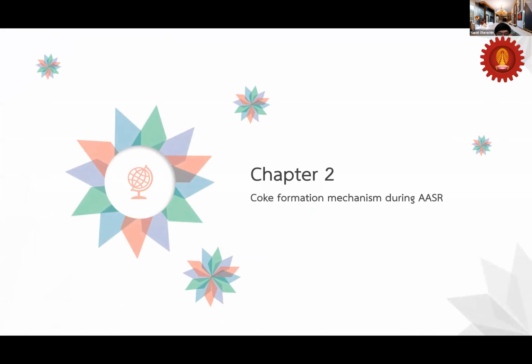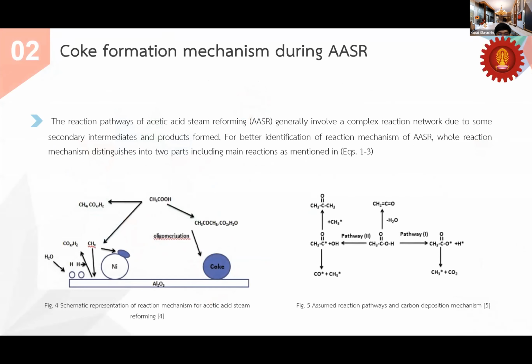Next is chapter 2. I talk about the coke formation mechanism during AASR. A simple reaction mechanism of AASR proposed in several studies is shown in figure 4 and figure 5. The dissociation of acetic acid over the catalyst surface is shown along with the proposed bifunctional mechanism. Dissociation of acetic acid over the active metal phase takes place by cleavage of the C-O and O-H bonds. Meanwhile, interaction with acidic support sites, a ketonization reaction might occur, followed by oligomerization of acetone, resulting in coke formation not only over the support but also over the metal-support interface.